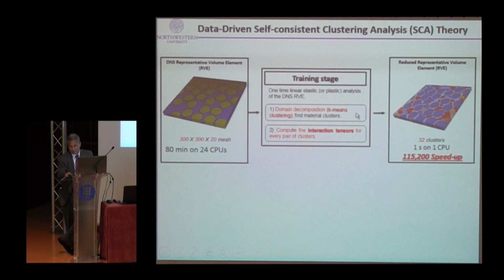There are a lot of clustering techniques that we have not studied, but we just use one called k-means clustering. And then you come up with the interaction tensor, how this interacts. Say, for example, based on that many degrees of freedom, I go down to 32 clusters. I can look at a similar response within 1 second using one CPU. So the speedup is tremendous in this case.